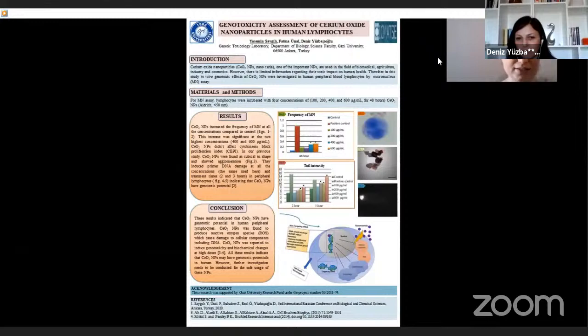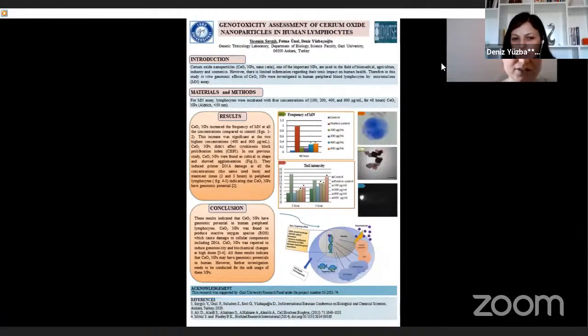For micronucleus assay, lymphocytes were incubated with four concentrations of cerium oxide nanoparticles. Cerium oxide nanoparticles increased the frequency of micronucleus at all the concentrations compared to control. This increase was significant at the two high concentrations. Cerium oxide nanoparticles didn't affect the cytokinesis block proliferation index.